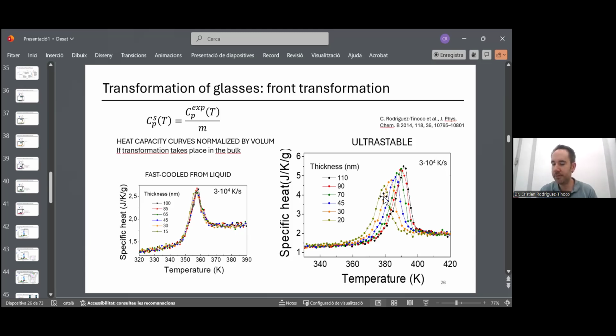Because you can have a very thin layer and you can have a very thick layer with different mass, but the transformation will take place in the same way. So a front starting from the surface and propagating into the bulk. So somehow if you divide by the mass, you have something which is not real. So this size effect you see here is not real. It's a consequence of a bad analysis of the data. Oh, okay. Thank you for these explanations.